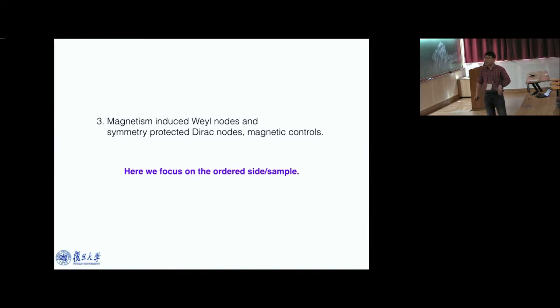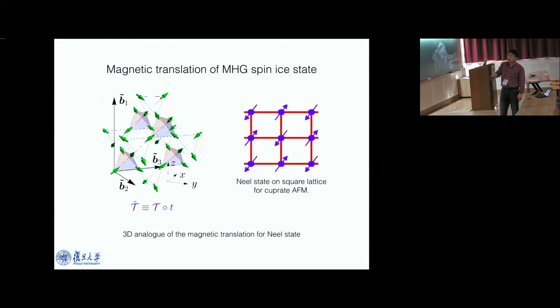This is the modeling of the microscopics. Before doing the heavy calculation, the system develops magnetic order. We use this magnetic order as the input condition to this model, and ask how the conducting electrons reconstruct their band structure in the background of this particular magnetic order discovered by experiments. This is the magnetic order discovered by neutron diffraction, and it turns out this magnetic order has a very special property. Although it breaks time reversal symmetry for obvious reasons, it also breaks translation symmetry. The crystal cell has been doubled, right?